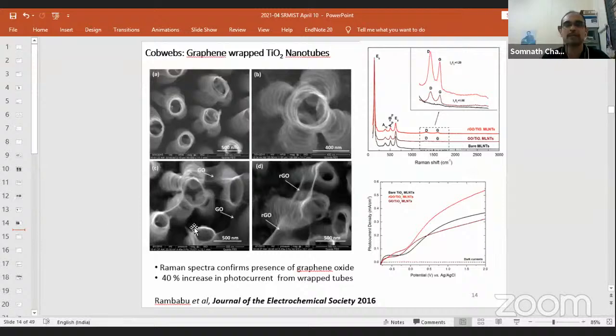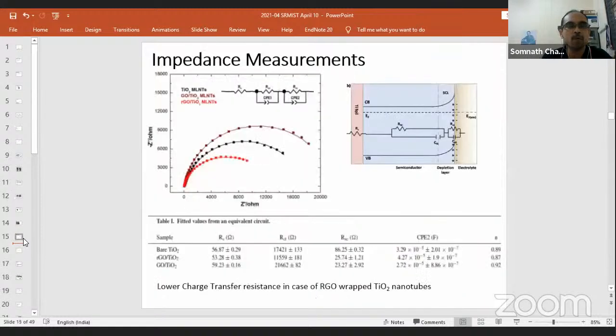When we ran one of the techniques, I'm not going into which one, we found this beautiful wrapping of graphene layers around the TiO2, as you can see in the lower two pictures. It was just like gift wrapping. You buy a gift and wrap it with gift paper, or at the airport they wrap your luggage with cellophane. I call this a remarkable achievement, in the sense that we found an increase in the photocurrent under sunlight, which indicated that we are able to harness more sunlight using the graphene wrapped TiO2 nanotube.